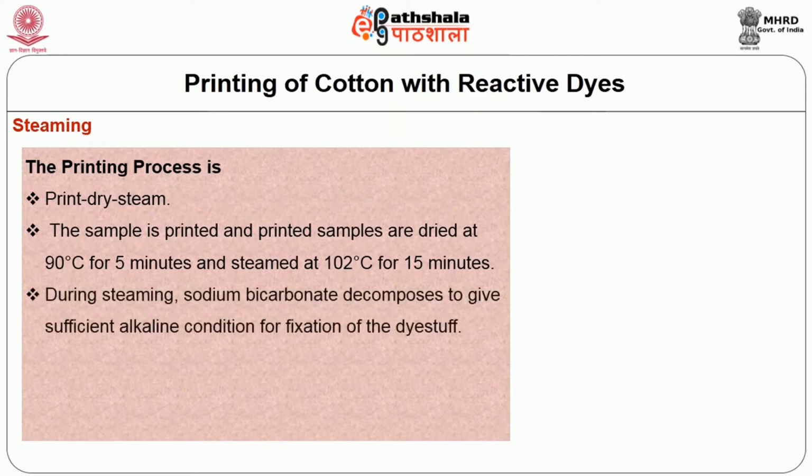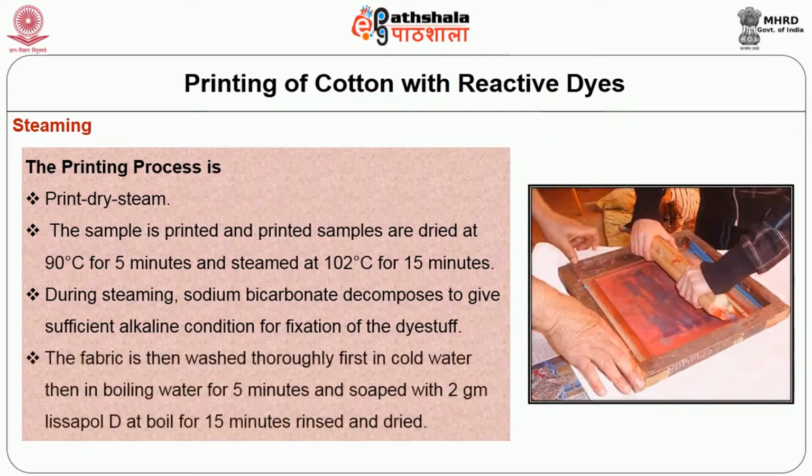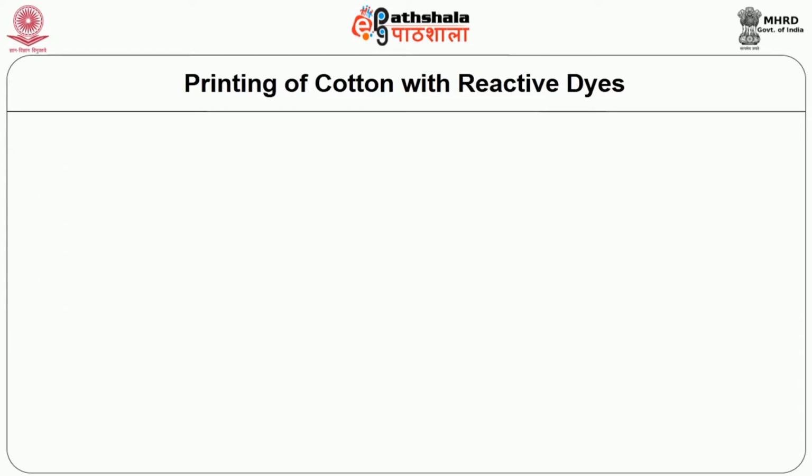During steaming, sodium bicarbonate decomposes to give sufficient alkaline condition for fixation of the dyestuff. The fabric is then washed thoroughly, first in cold water, then in boiling water for 5 minutes, and soaped with 2 grams Lissapol D and boiled for 15 minutes, rinsed and dried.